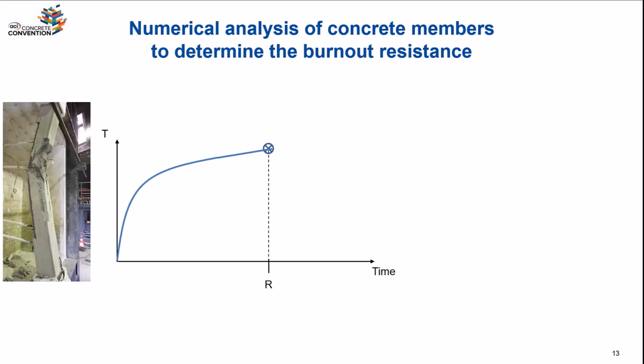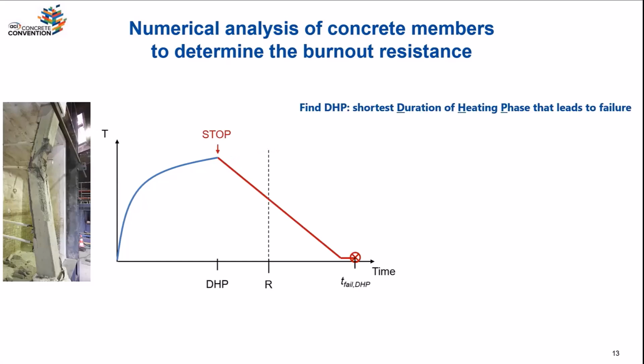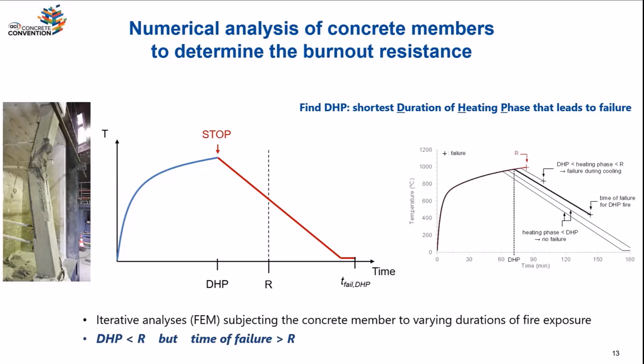The question we want to look at is, should we stop the heating earlier, but keep the load applied on this column? Okay, but we stop, you see, at a time that's earlier than standard fire resistance, and then there is a cooling phase. Would the column survive or would it fail? And what we want to do is to repeat this analysis for different values of DHP, of duration of heating phase, and differentiate between the fires that lead to failure and the ones that are survived.